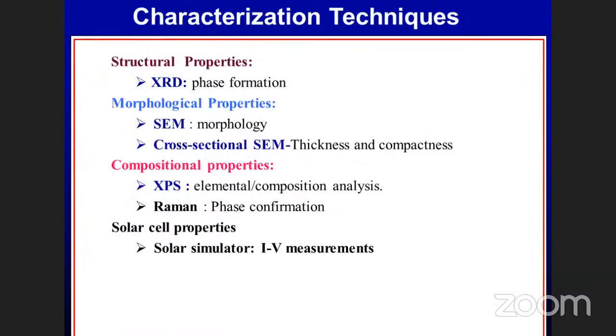Yeah, these are some characterization techniques I use to characterize my material. That is XRD for phase formation. SEM is for the morphology investigation. Then cross-section SEM in order to study the thickness of the material. See, the thickness is very important in the solar cell. That's why the optimum thickness is just like 1.5 to 2 micrometer. Okay, we need this one.